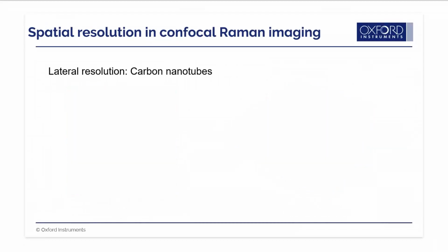If we talk about microscopy, we are also interested in the lateral and vertical resolution. A simple way to estimate and test the resolution of a microscopic configuration is by analyzing features much smaller than the effective resolution. To test the lateral resolution, meaning the resolution in the focal plane, carbon nanotubes with a diameter of a few nanometers are perfect.